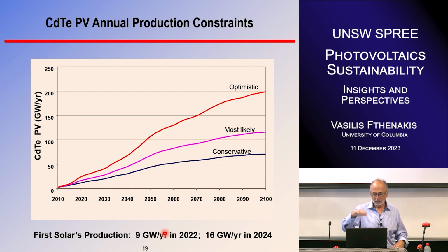With these primary and secondary resources giving a high, perhaps, ceiling on what could be the production of cadmium telluride, we still have these projections. We can make these projections. Again, optimistic, most likely and conservative correspond to different efficiency and different film thickness assumptions, according to different scenarios of production. I think this company, the only big company in the world that produces cadmium telluride, is close to 16 gigawatts now, with a new production of about 7 gigawatts in India. So we're about here, along the conservative one, but not far off what we projected about 10 years ago.